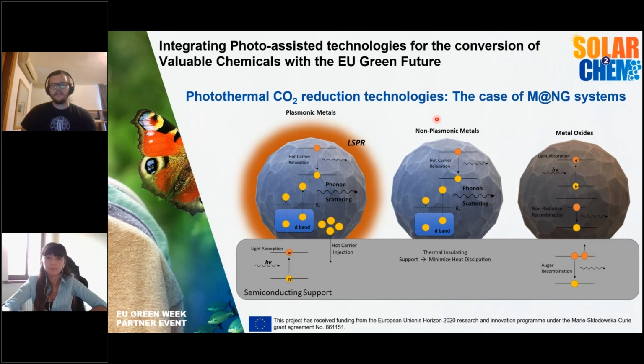So just to understand better what photothermal catalysis is, compared to photocatalysis, it's not directly dependent on the charge separation by light irradiation, but rather on nanoheaters induced by light irradiation. What this means is basically that it's a lot closer to the classical thermocatalytic systems that we already have. There is a lot of progress out there in the scientific literature, and also there are attempts at bringing it out. So technically, we're not starting from zero with this technology. The only difference is that instead of conventional heating, the heating is actually obtained through light irradiation and at the nanoscale level.